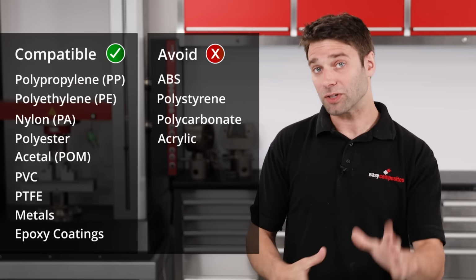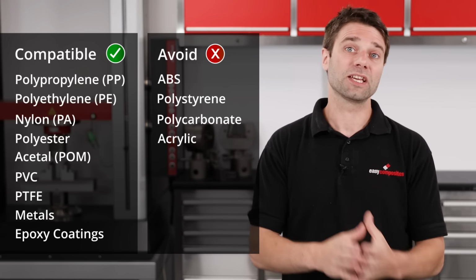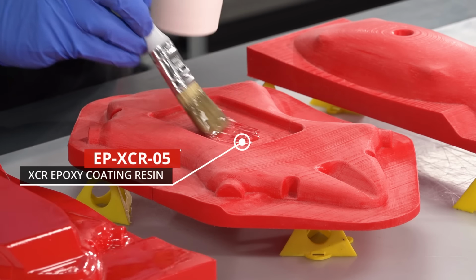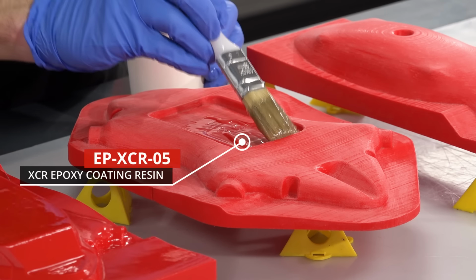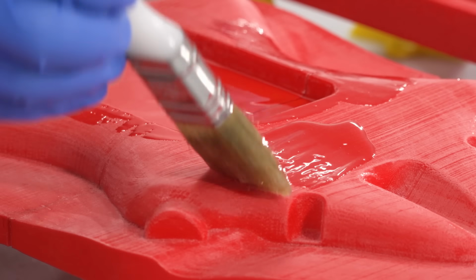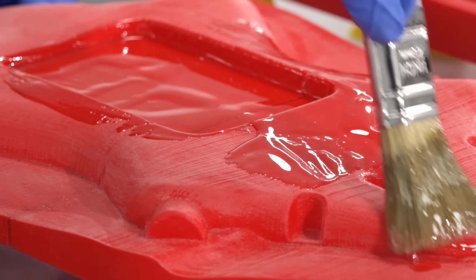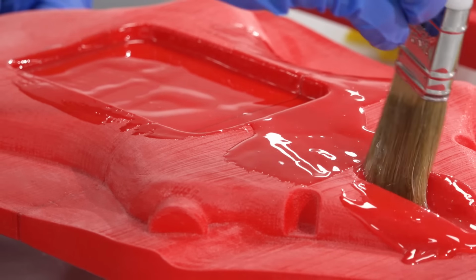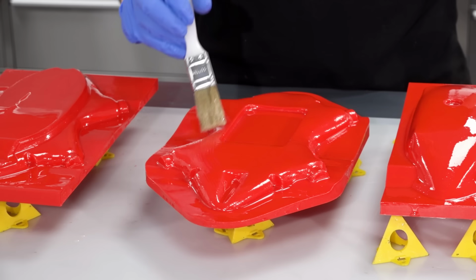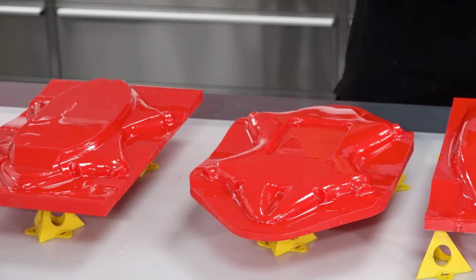Then there's epoxy coatings. Sealed epoxy coatings like the XCR coating resin make for a fully compatible pattern surface, and their excellent leveling and bonding characteristics make them probably the best choice if you're using a 3D printed pattern and want to smooth out those layer lines.